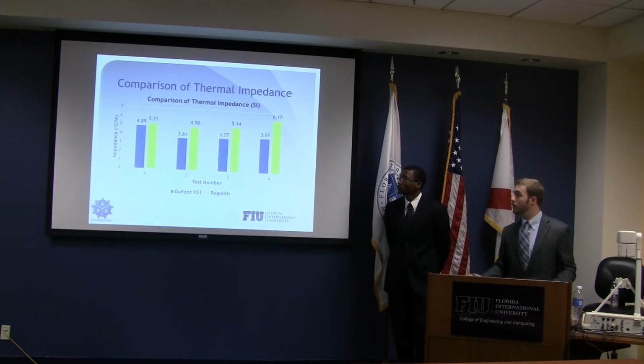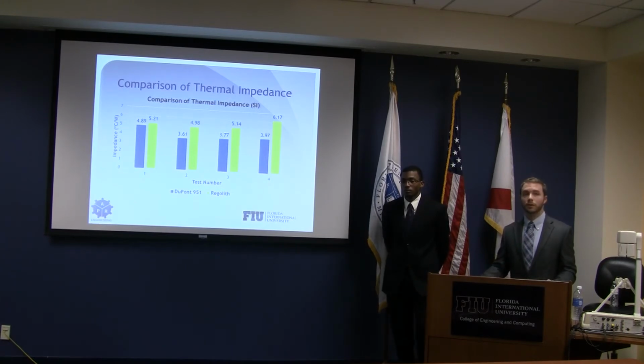These are the 4 different tests that we had. It's 120 different data points for each material. And as you can see, for the DuPont 951, the last 3 had a very low standard deviation, and the opposite is true for the regolith. The first 3 had a low standard deviation.